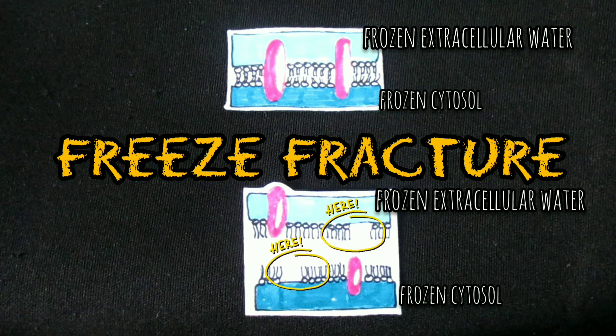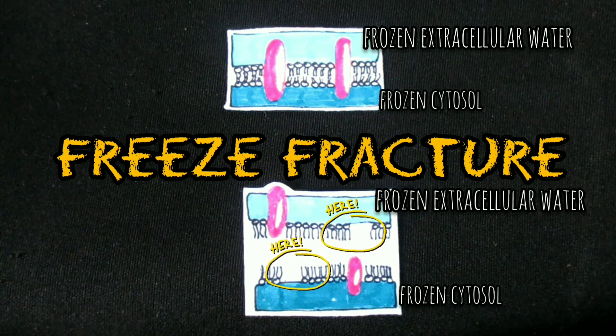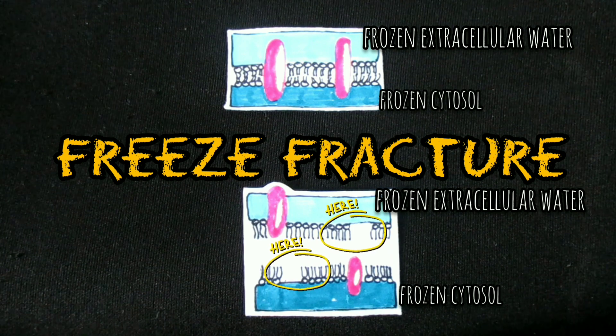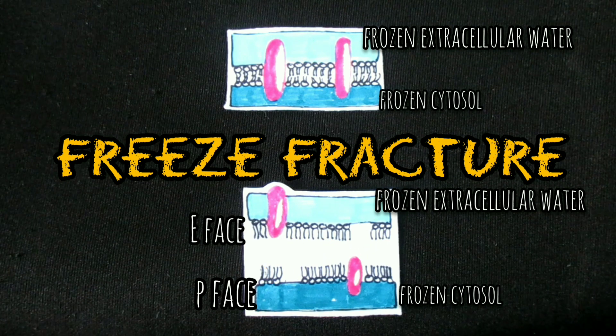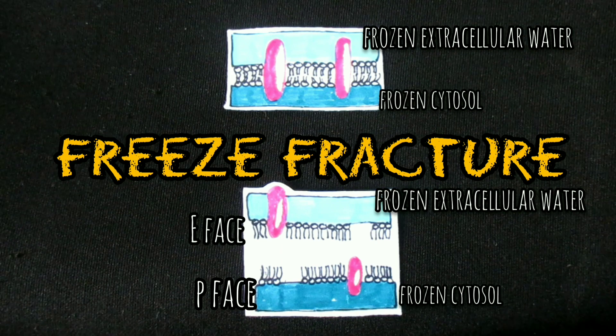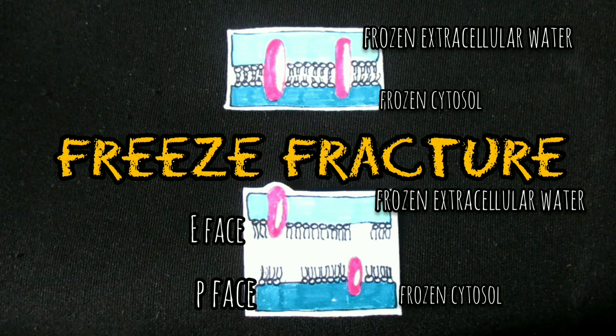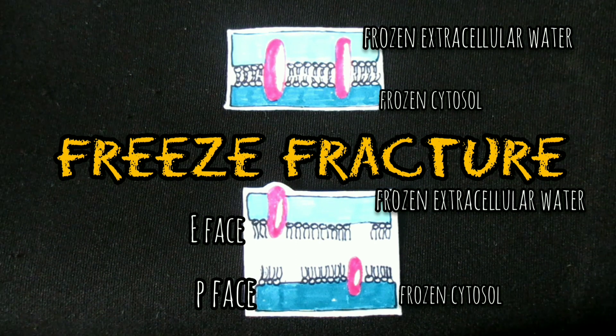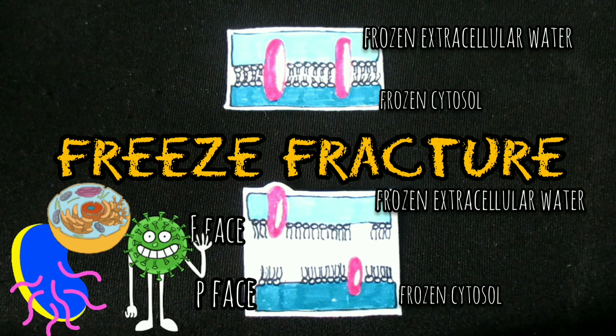The frozen fractured specimen is exposed to a vacuum at an elevated temperature for one to a few minutes, during which a layer of ice evaporates from the exposed surface. Once some of the ice has been removed, the surface of the structure can be coated with heavy metal and carbon to create a metallic replica. This allows for the analysis of not only the membrane structure but also of intracellular components, providing detailed structural information on bacteria, viruses, and large cellular protein complexes.